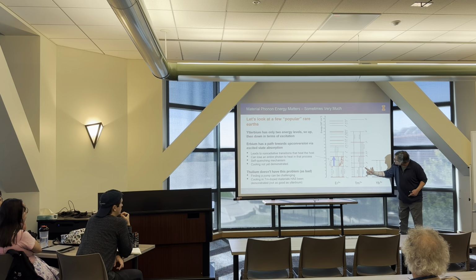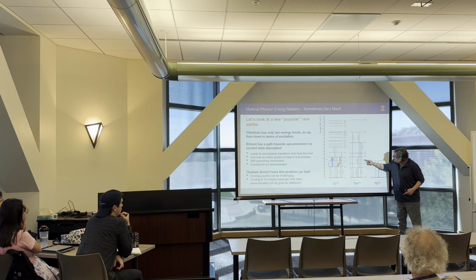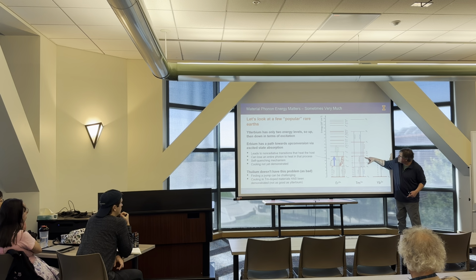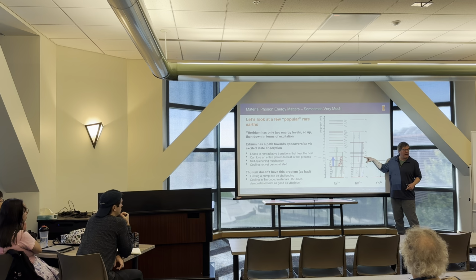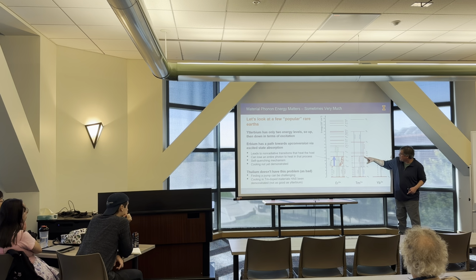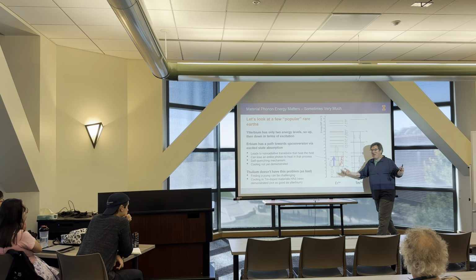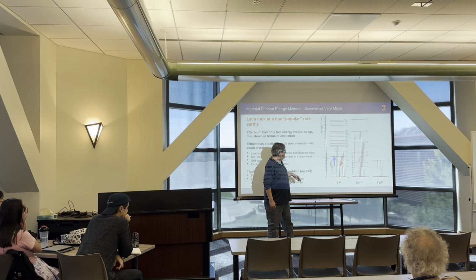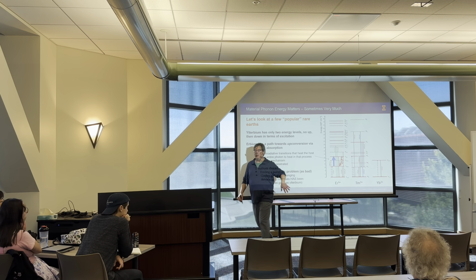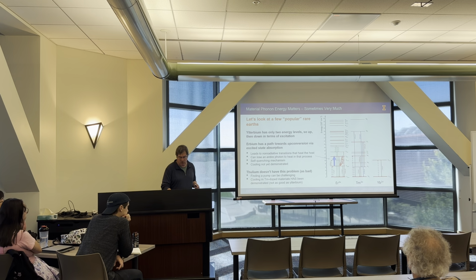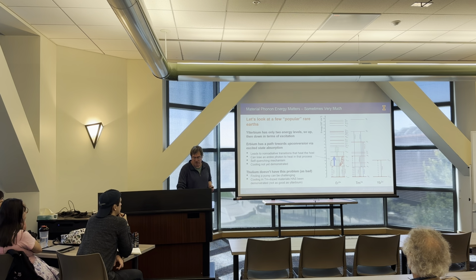Thulium potentially has the same problem, but if you take a look at the energy spacing here and here, absorbing a second photon doesn't quite get you to this level. And so this means that our thulium system potentially can cool, and indeed it does. Erbium does not cool. Nobody's ever observed erbium cooling in the past, whereas thulium, yes.